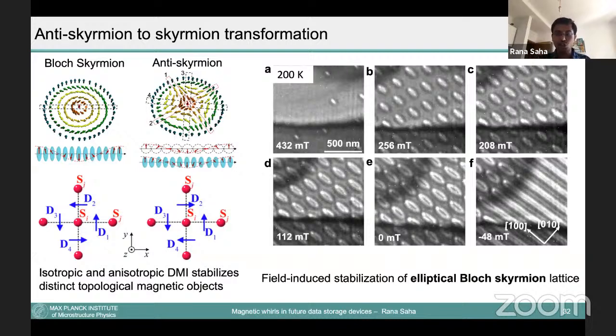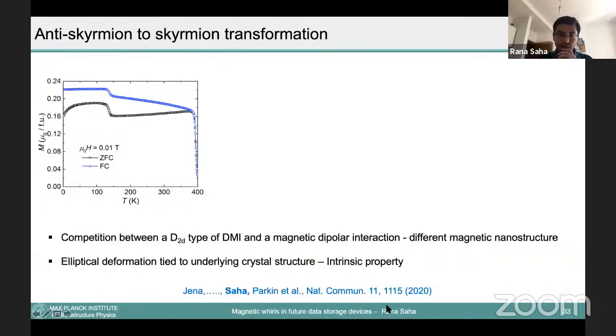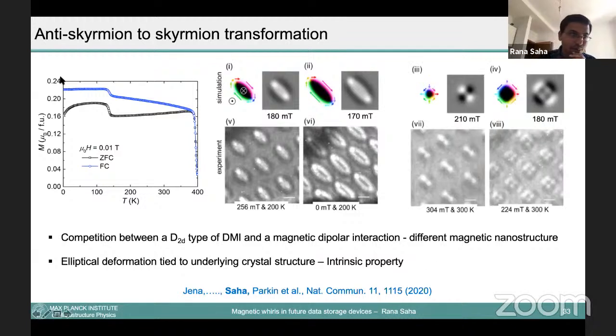So what is the implication of these two types of spin textures? You have the temperature-dependent magnetic data. Here you see the magnetization value is higher, here you have a lower magnetization. When you have higher magnetization, there is something called magnetic dipole interaction. When you have a stronger dipole interaction, you can make the antiskyrmion stabilize in the form of a skyrmion texture, which is here. But when you have a lower magnetization, you have a lower magnetic dipole interaction, so the antiskyrmion survives. In this way, in the same material, you can have two different types of topological structures.